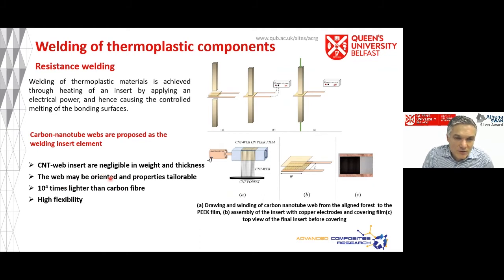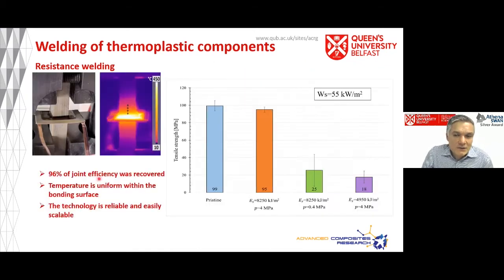We can control the properties of that conductivity, and of course, they're also very, very flexible. And if I look at the results here, we've looked at different energy requirements and different pressures, and you can see that you can pretty much recover the strength of a pristine sample with a combination of pressure and energy.